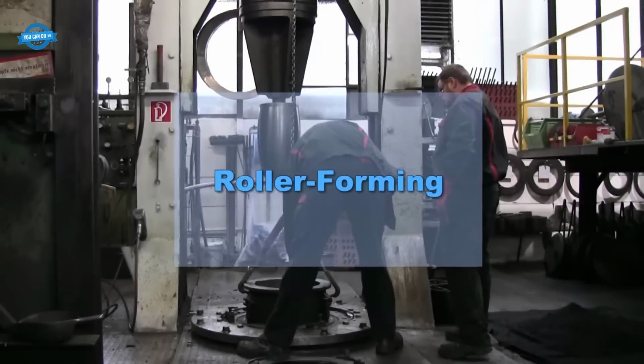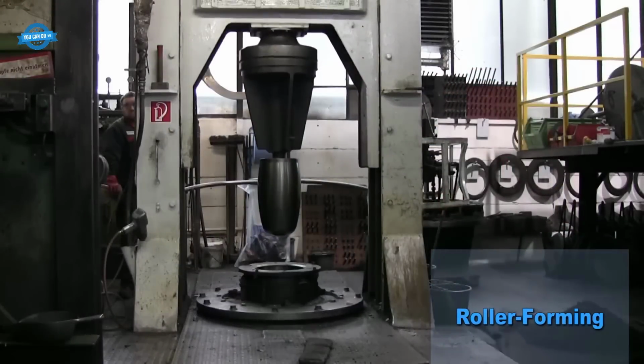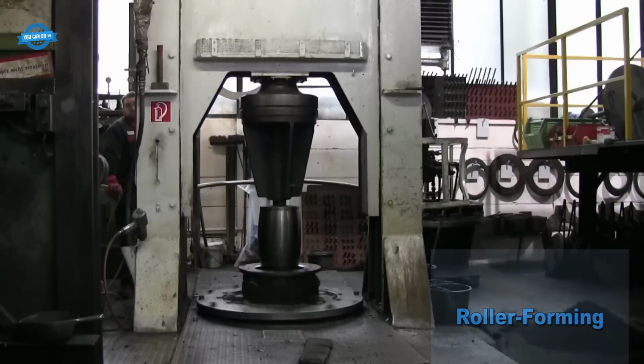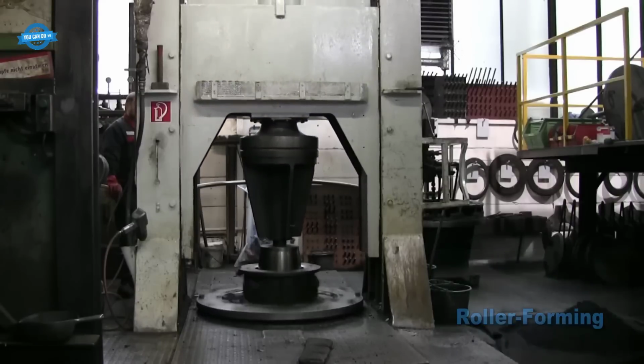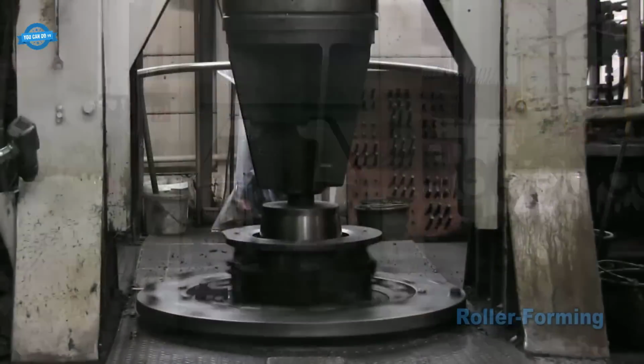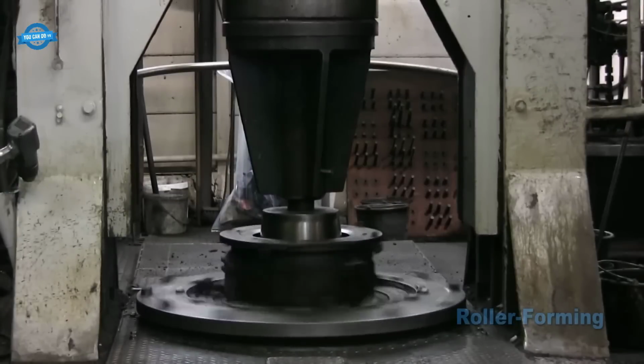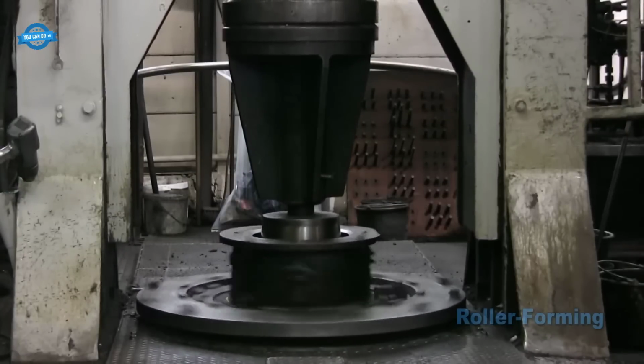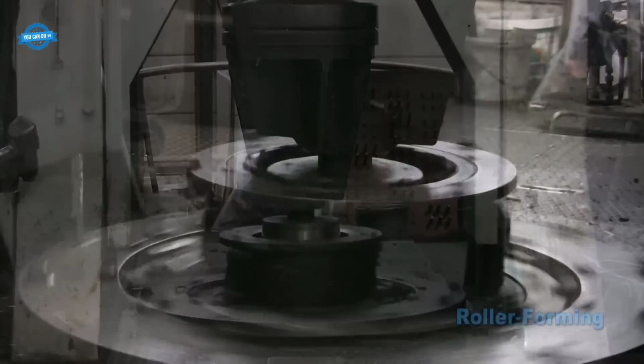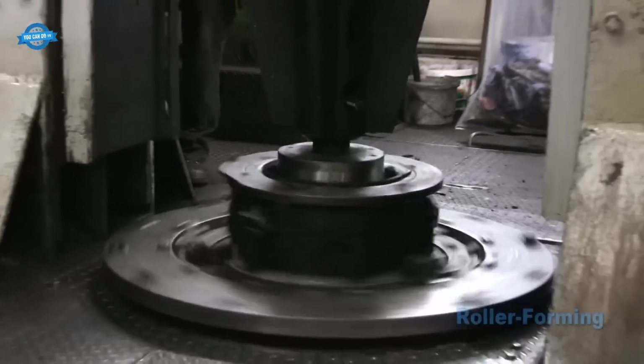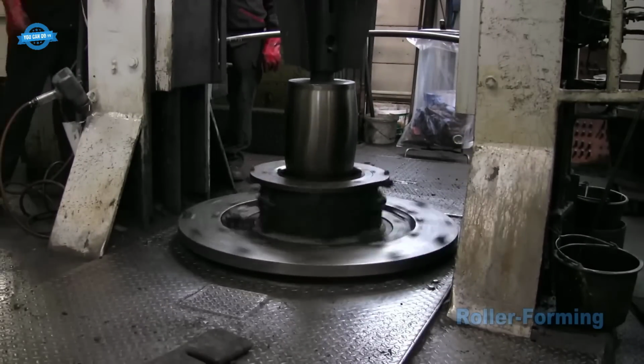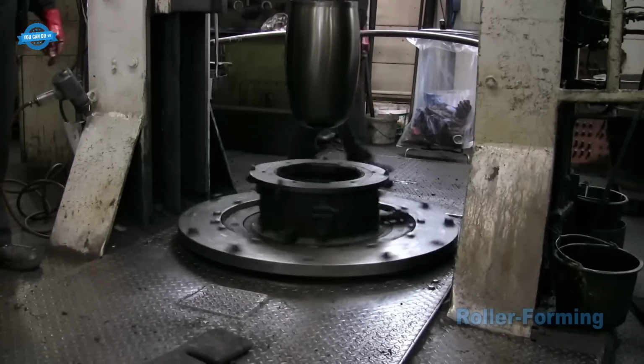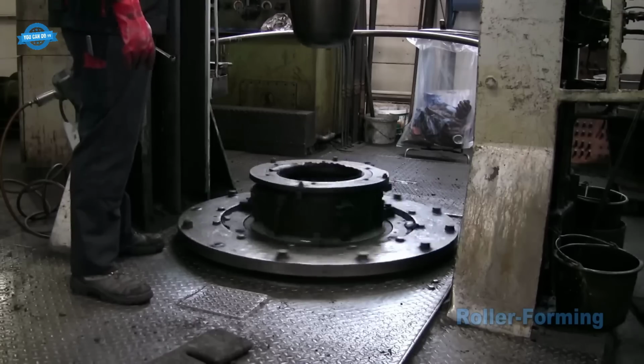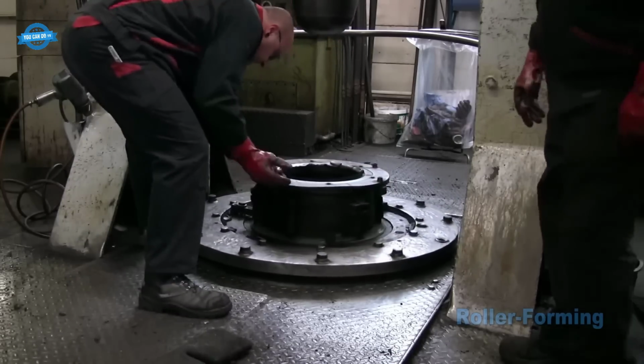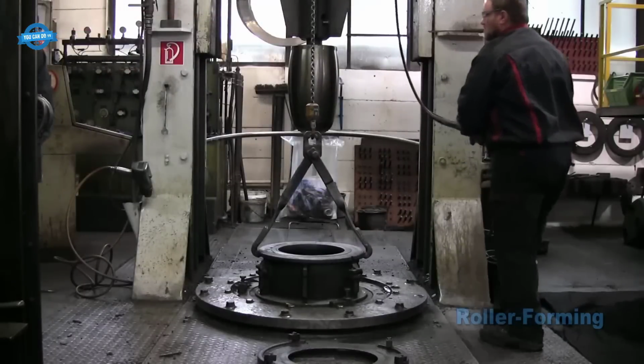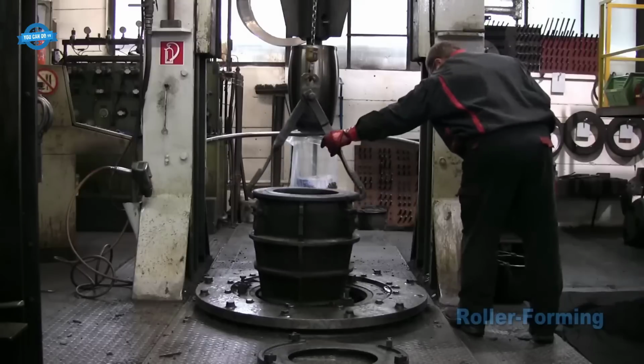Roller forming. The process begins by filling the mold with the requisite materials, after which a stainless steel roller is introduced into the spinning mold. This roller applies controlled pressure to the material, effectively displacing it and compressing it onto the mold's bottom and sides. The result is a crucible characterized by exceptional thermal conductivity, impressive thermal shock resistance, robust mechanical strength, and outstanding refractoriness. Additionally, these crucibles boast exceptional resistance to damage caused by fluxes, making them indispensable in high-stress industrial settings.